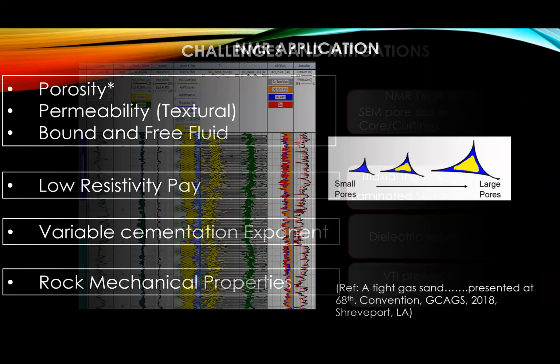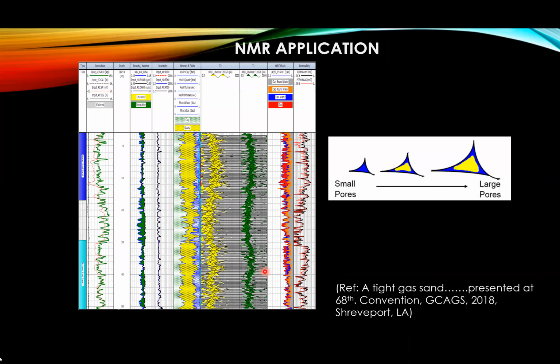So first, let's look at the NMR, and this is also a paper presented at the GCAGS in 2018 in Shreveport, Louisiana. I'm not going to go track by track, but this track is showing the NMR distribution. You remember, the time increases from left to right, and this is another track for NMR. This is the T1-T2 distribution. So mostly we're going to look at this T2 distribution for now. When you see these yellow humps here, these are representing very early time. So ideally you think that those are the extremely small pores, which could be from the clay-bound water, right? So that's the clay-bound water signal or extremely small pores.